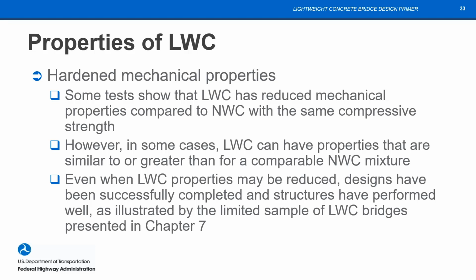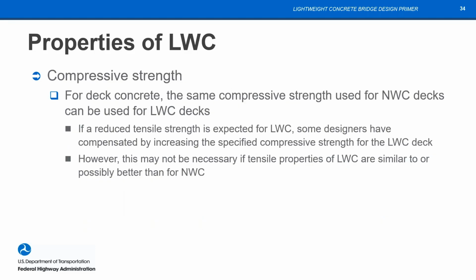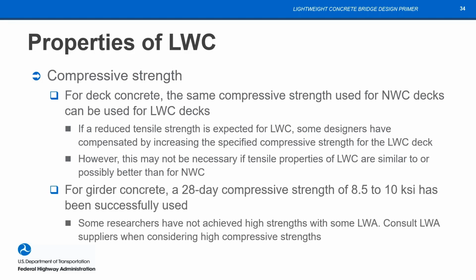That's the most significant one, but many of the others are essentially similar. And in some cases, lightweight concrete can even have better properties than normal weight. So there's a lot of information in the primer that you can learn more about. For compressive strengths, you should check with available lightweight aggregate sources to find out what's a reasonable upper strength. And in some cases, you can make some compensation, as indicated here.